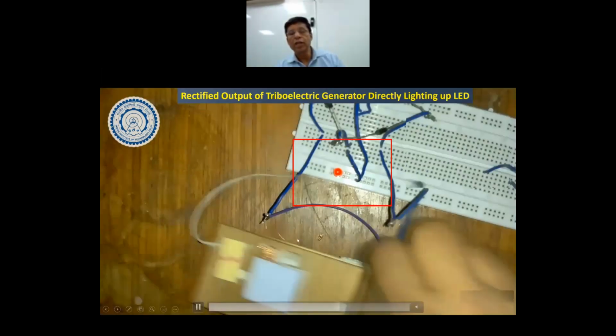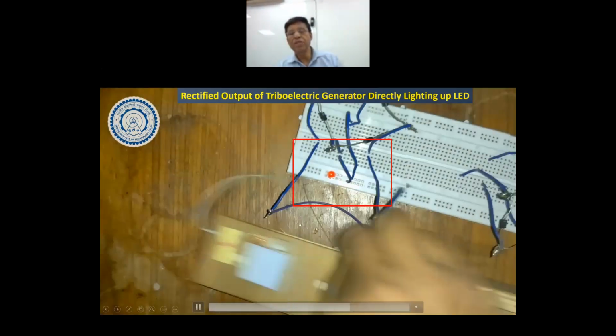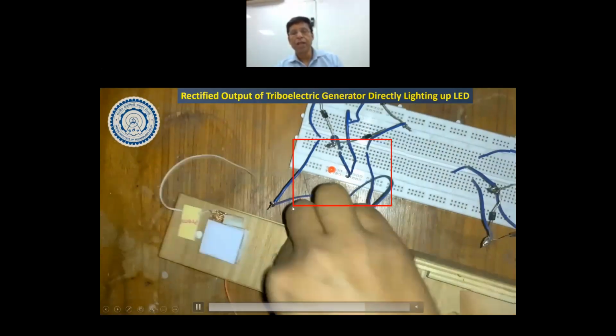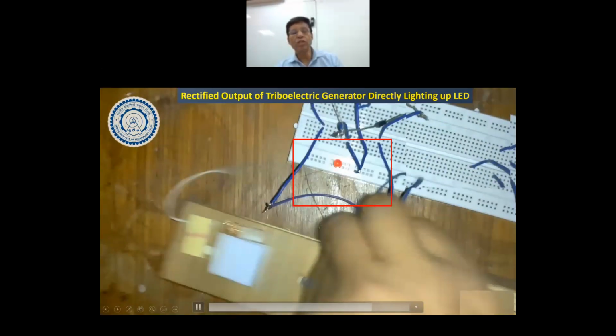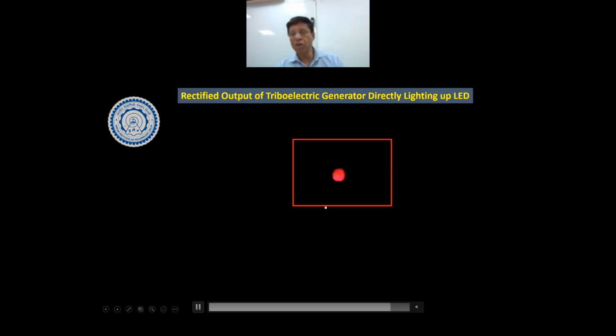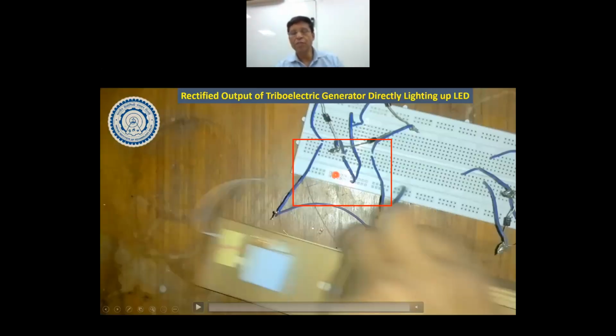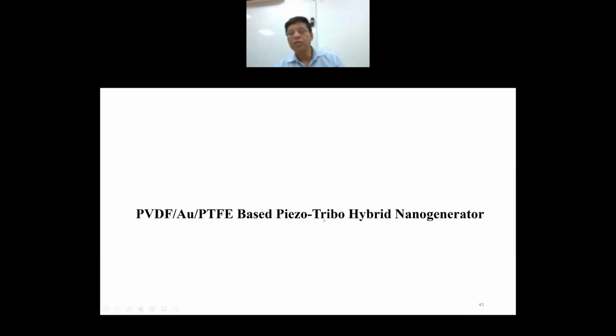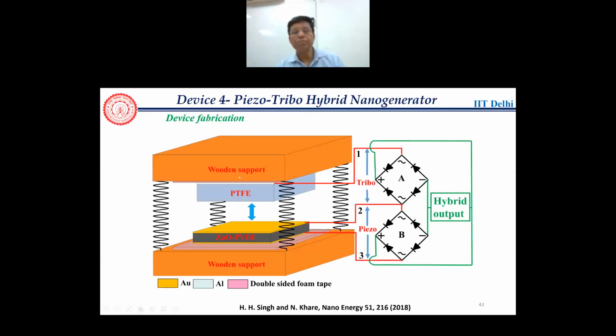And the way it is done is that first we make this PVDF DMF solution, and then we add this sodium niobate, and we also add this RGO in this solution, and finally we get this kind of flexible film. So this flexible film has both this PVDF and this reduced graphene oxide. And what is the significance of adding these two? I will explain in a minute. So these kinds of flexible films are formed by this method.